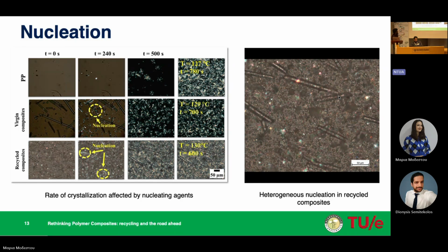And coming to the recycled composites, both the fibers and the thermoset residue matrix help the crystallization process even more compared to the virgin composites. As you can see here, the time taken to fully crystallize is somewhere around 600 seconds, which is almost 10 minutes, or even 1 to 2 minutes below that of pure polypropylene. If you extrapolate this to an industrial level, this is obviously a significant number.